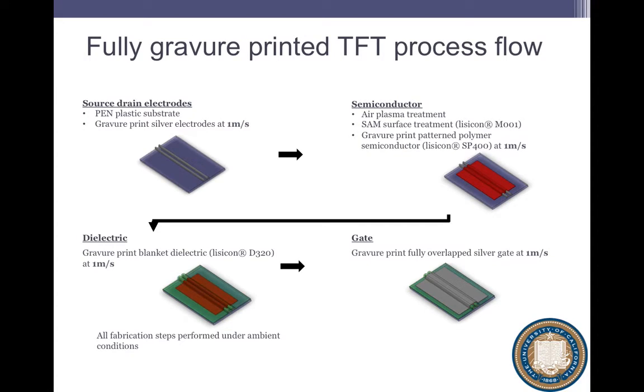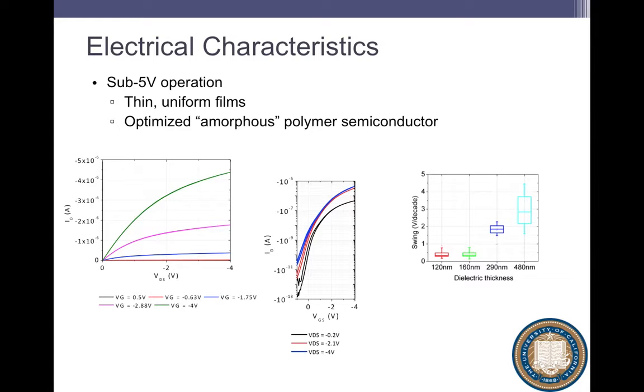And so here's the first device that I'm going to show you. This is a printed transistor. We print source drain, print semiconductor, print gate dielectric, print the gate. Every layer is gravure printed, so printed at 1 meter per second. And if you look at what our transistors look like, they work really well. I mean, they're printed on plastic. They run at low voltages. They give switching characteristics that are on par, in fact, better than amorphous silicon transistors. And today, we have these running at over 10 megahertz. On plastic, printed at 1 meter per second. So we really can produce some pretty decent devices this way.